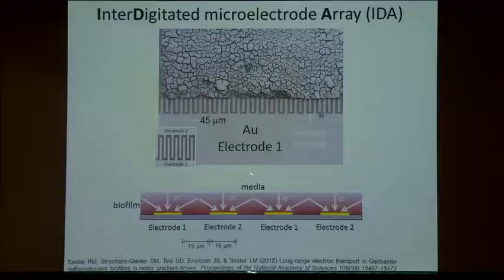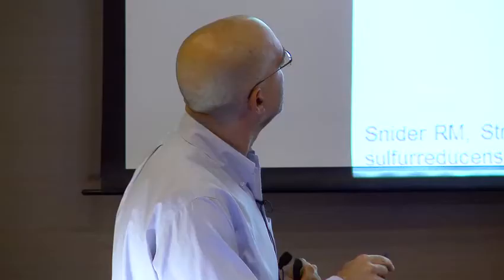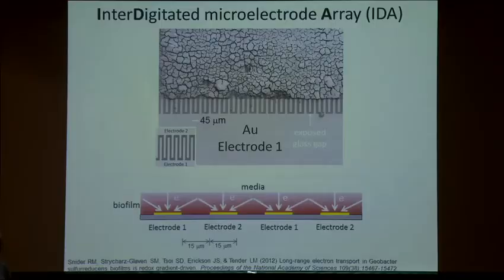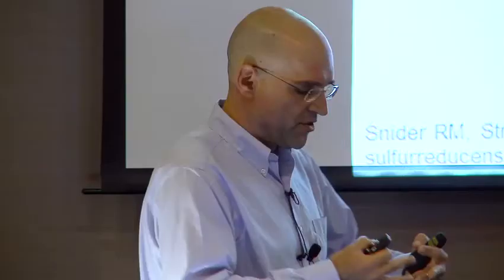deposited. And so what you have here is a gold surface evaporated onto a glass slide. And created either by mask or by etching is simply a pattern where you remove in this sort of rectilinear fashion some of the gold, creating a gap, bisecting your gold electrode into two electrodes. And by using this sort of undulating or rectilinear gap here, what you're creating are two sets of microelectrode bands that are interdigitated. I don't know, they're interlocked.